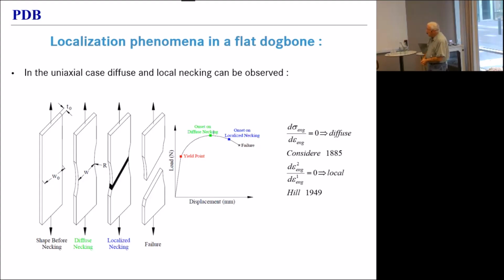fracture. Now, the criterion for the onset of diffuse necking has been known since 1885. It was Considère who identified it with the maximum of the force displacement curve, or to put it differently, the maximum of the engineering stress, engineering strain curve. Again, Rodney Hill identified the start of localized necking as the point where the second principal strain stops growing as the first principal strain is further increased. And at that point, the only thing that your material can do is thin, and obviously the process accelerates very rapidly from there on.